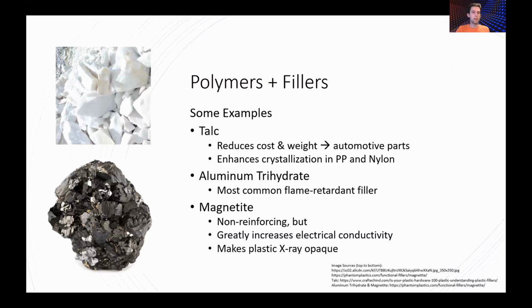For example, talc is a very common filler because it is cheap, plentiful, and low density. It is used in many common plastics. For example, it is used to increase the stiffness of polyethylenes and nylons and can be used to make up as much as 40% of polypropylene-based automotive parts. A couple other interesting examples are aluminum trihydrate, which is most commonly used as a flame retardant filler, and magnetite, which can be used to greatly increase electrical conductivity and make plastics opaque to X-rays.